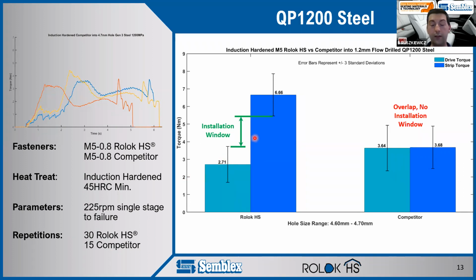What's interesting here is that an induction hardened part only has high hardness on its lead threads. Its lead threads were 45 Rockwell C minimum, but its body threads were equivalent to class 10.9. Your lead threads are what control your drive torque, but it's your body threads that control the failure torque. So what actually happened here is we had a 1200 megapascal steel, and our fastener body was only about 1000 megapascal. So the steel was actually stronger, and we got a very unusual failure mechanism. We actually stripped the threads off of the fastener itself, off of the male part.